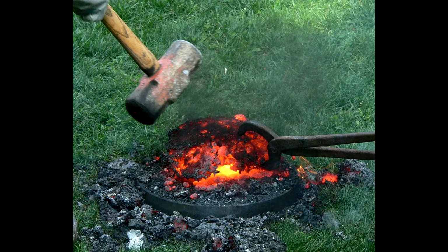This process can be discouraged by the use of a flux, which mixes with the surface impurities, both forming oxides and also slag being forced to the surface, lowering their melting point below the temperature of the metal. This is crucial to prevent the impurities, because they form on the outer edge of the iron where the weld is happening, from fouling the weld, burning it, and rendering it brittle. It can also, as I understand it, allow us to get back some of the iron in those iron oxides, and prevent further loss of metal due to oxidation. There is some evidence that fluxes in iron welding were in use by at least the Roman period, and certainly by the Middle Ages, were standard smithing practice.